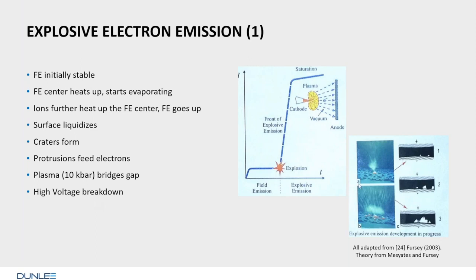Well, these are cartoons. They are not really physics theory, but they show what this is all about. Initially, we have field emission. The field emission is more or less stable, but once the emitter gets a little unstable, it heats up and starts evaporating. So it sends gas into the space. This gas is subject to electron bombardment and turns into ions. Ions go back to the origin of the field emission, heat up the surface, and energy is put into the field emission center or its environment. So the surface liquefies, and that creates more electrons because the liquid is pulled out of the surface. Craters form, and protrusions feed electrons.